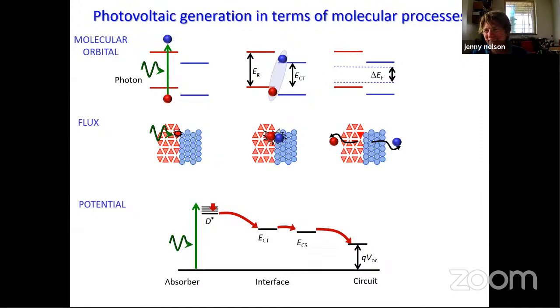Okay. Sona Das has asked, what is the typical exciton binding energy in organic semiconductors? Well, it's quite a hard question to answer. I'm not sure that it's really known. But the typical value, I might hand over to Satish to answer this. The typical value that we think about would be some tenths of electron volts, so maybe 100-300 millielectron volts, and that's something we know empirically rather than by any direct measurement. For example, we know that there is an offset in electron affinities which is big enough to separate charges. So that type of thing. So the easy answer is 0.1 to 0.3 eV.